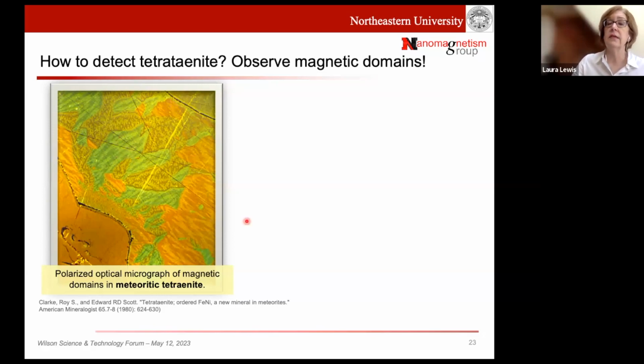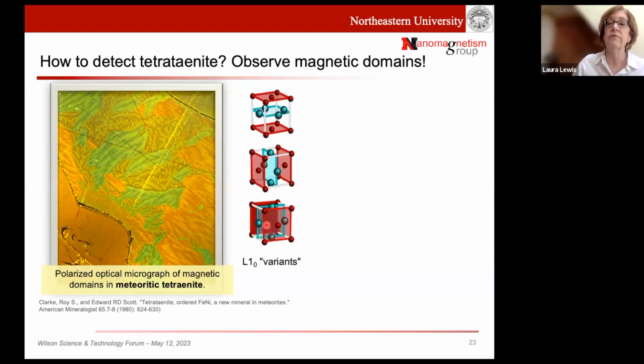You do not see any 90-degree domain walls. So what you're actually seeing are the three variants of tetrataenite that grew naturally in this material. Down here, this thing right here is not magnetic. This is probably some kind of iron sulfide.